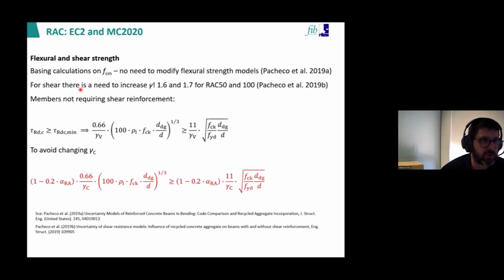Flexural and shear strength. So flexural strength depends on compressive strength. There is basically no change there. In shear, there were also studies on databases that show that the partial factor for shear should be increased, but linearly, going from 0 to 100% recycled aggregates, from 1.5 to 1.6 and 1.7. So we opted for, instead of changing a partial factor, which is a bigger thing in Eurocode, making this linear decrease of 1 minus 0.2 alpha, and then the typical expression for natural aggregate concrete. Again, if we go to 0.4 of recycled aggregates, which is the limit, this is an 8% reduction in members not requiring shear reinforcement, but it's there.